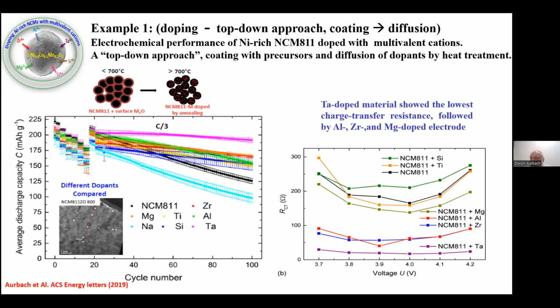What is nice is that we get good stability. And now the chart shows cells with different electrodes, the same material but with different dopants. Here we compare capacity and we cycle it over hundreds of cycles, and you can see very clearly the difference. We see that the reference without doping has very fast capacity fading, and some dopants are better than the reference. In this experiment, the best doping was by tantalum. And interestingly, when you have good doping and good electrochemical stability, it affects the structure.